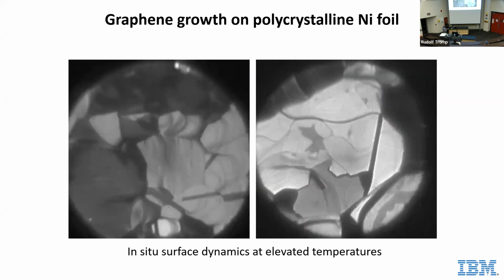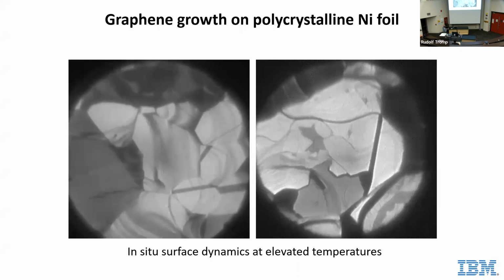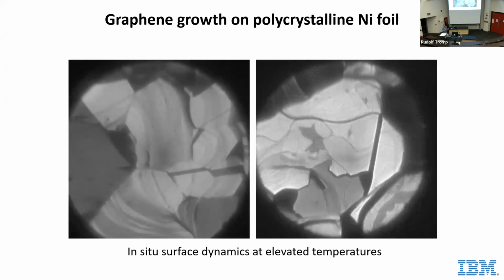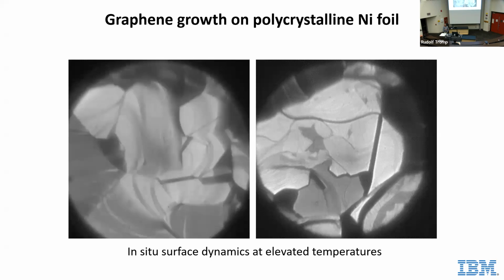At high enough temperature, the oxide comes off, and we see atomic steps on the surface, right? So we just cleaned this thing up. And I hold it there. This is probably at about 800 Celsius or so. This was a real-time movie. So this piece of the whole experiment took 10 seconds to do, right? And if you wouldn't have this real-time imaging capability, you would have missed the whole thing.